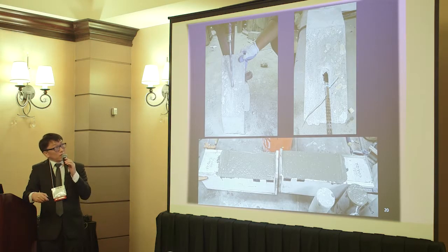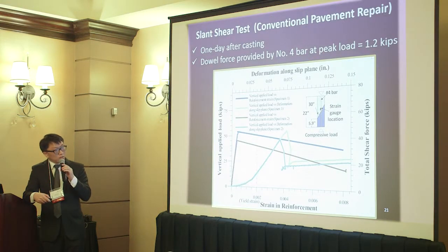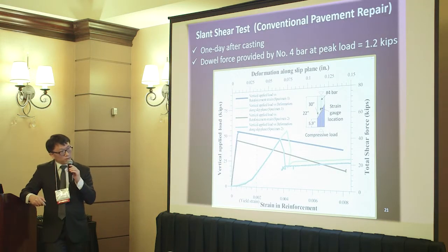For conventional concrete, we follow the standard procedure. This is a saw-cut smooth surface, and we drill holes, put the reinforcing bar inside, and use epoxy to grout it. That's the typical way they do that. We also have strain gauges here, so we can measure the deformation, or indirectly the stress in the rebar, and then cast the top part. I will just show some results for the plain concrete.